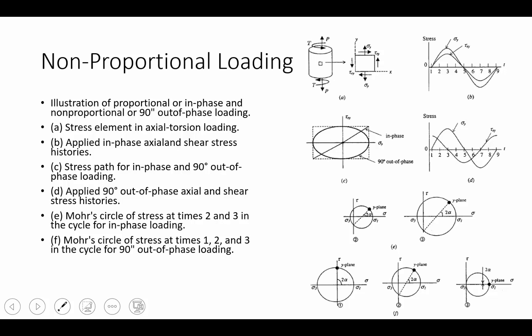Here is a schematic that illustrates this process. In sketch A, we have a stress element subject to tension and torsion. In B, we see in-phase axial and shear histories where the peaks are at the same point. In in-phase loading, we get a nice straight linear relationship — a fixed slope between the axial stresses and the torsional shear stresses. But when we're out of phase, we do not have that constant slope. Instead, we produce an ellipsoid shape dependent on the amount we are out of phase, which in this case is 90 degrees.